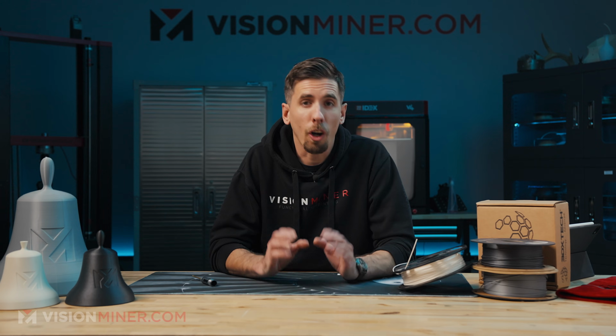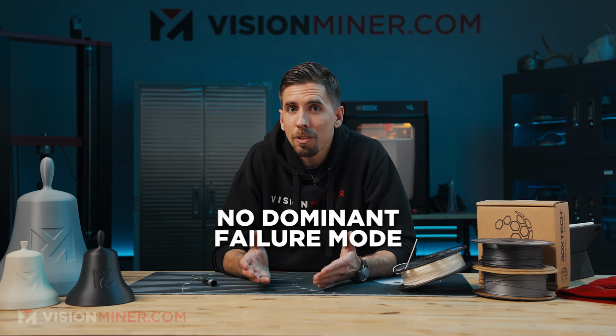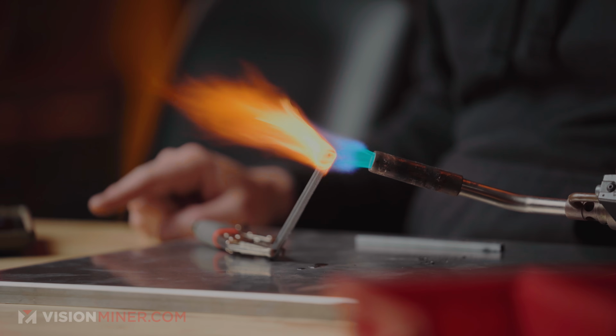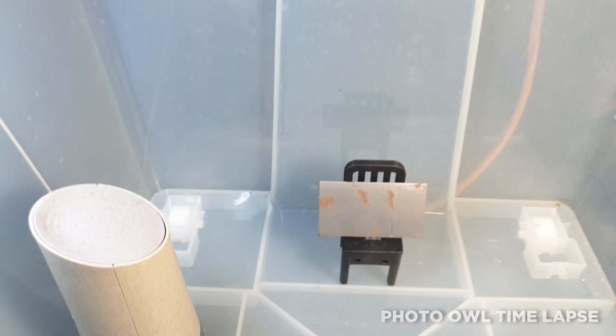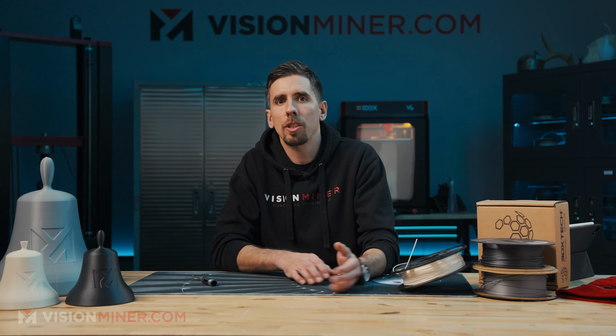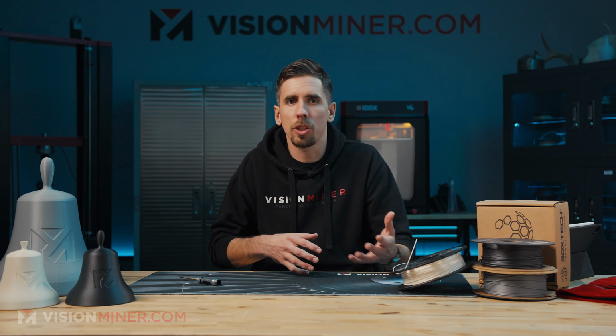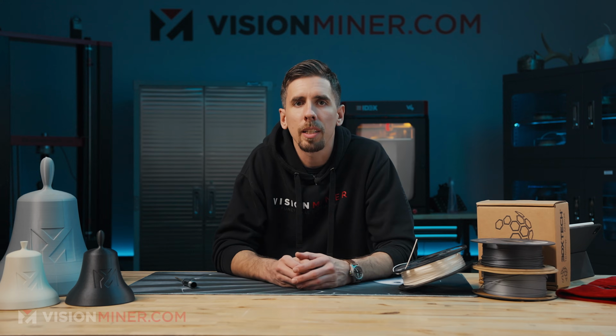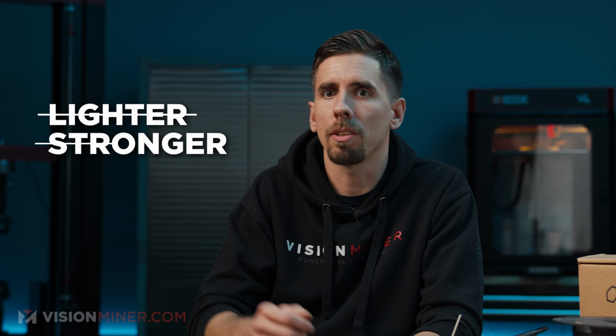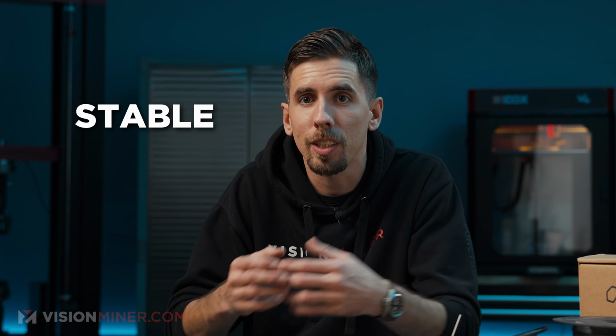You could design a system, theoretically on paper, perfectly, and still watch it fail 6 months later actually in the field. Now the hardest part was that there wasn't a single dominant failure mode. Sometimes heat killed the part, sometimes it was chemistry attacking it, sometimes it was just slow dimensional drift over time from the moisture and the other elements of the environment. Engineers weren't asking for a lighter material, they weren't asking for a stronger material. They just wanted a material that simply stayed exactly the same over time, no matter what it was exposed to.